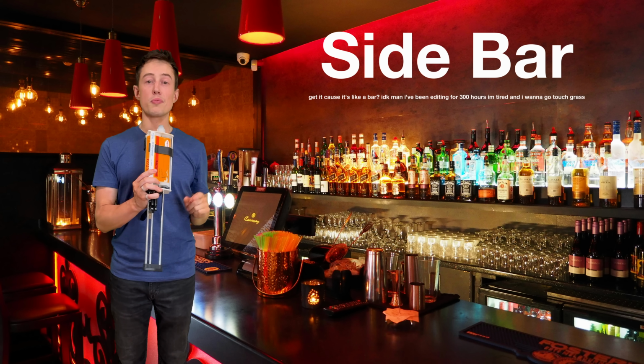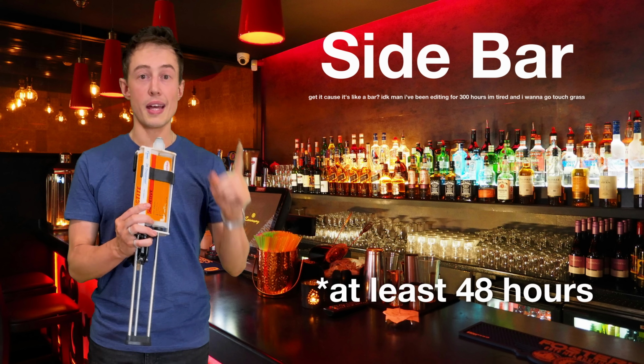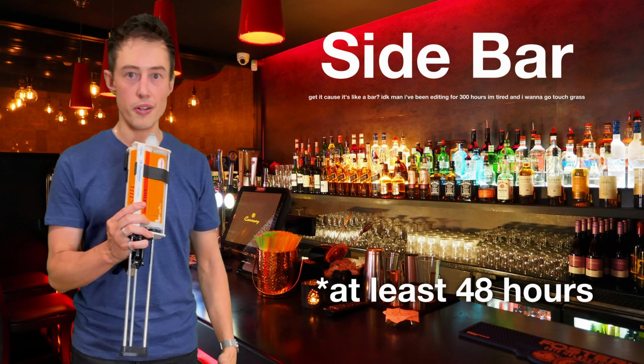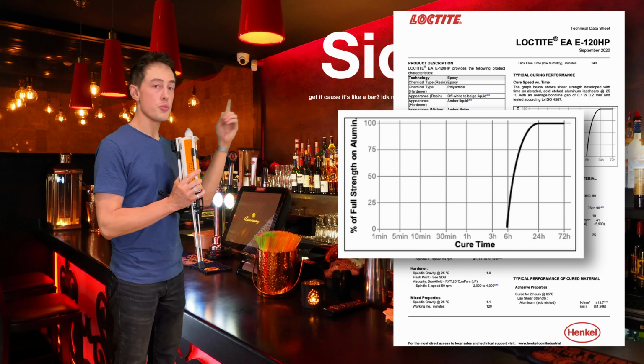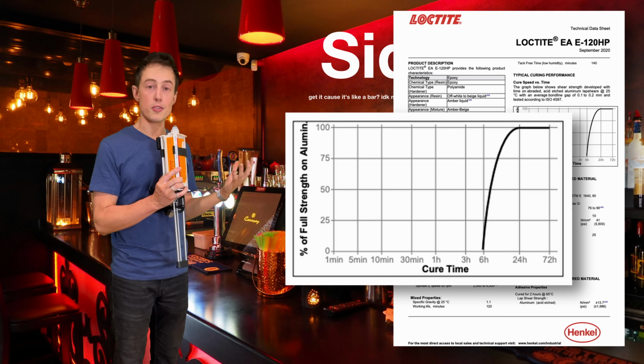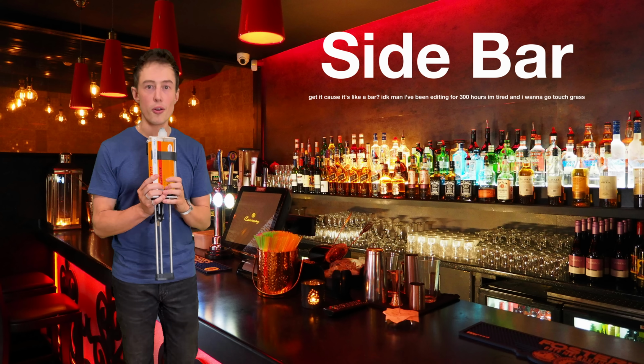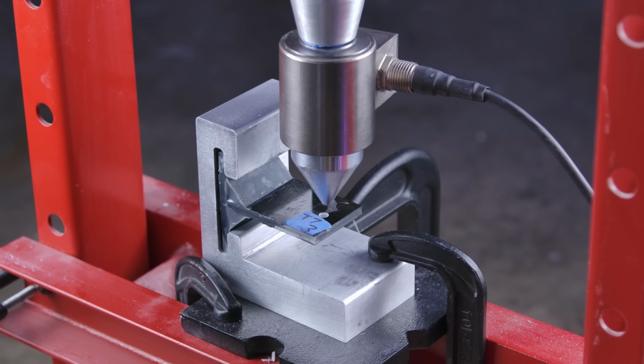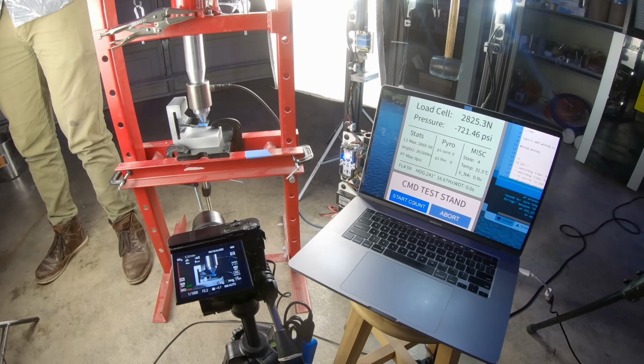Sidebar, all of these tests were run 48 hours after bonding. That is a variable I controlled for. The epoxy should cure to full strength within 24 hours, but 48 gives us a little bit more margin. Okay, sidebar over. After demolding the 40 grit samples, I loaded them up and let it rip.